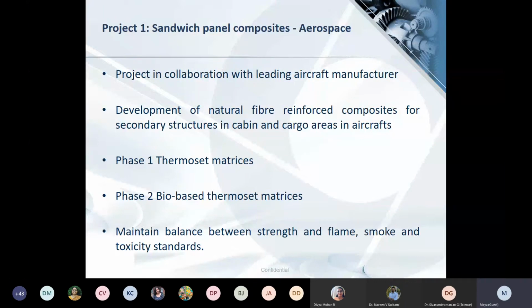You have glass reinforced phenolic sandwich panels mainly used in the side panels, and glass reinforced epoxy is used for the floor as well because of greater strength requirements. Currently the side panels are made from glass reinforced phenolic resin, and the purpose of the project was to replace the glass with a woven flax fabric. Phase one of the project focused on a phenolic resin, which is a thermoset matrix, and phase two was to replace the phenolic with a bio-based thermoset matrix. Here we used polyfurfuryl alcohol resin as the matrix. The challenge was to maintain the balance between strength and FST requirements, which are the flame, smoke and toxicity requirements.